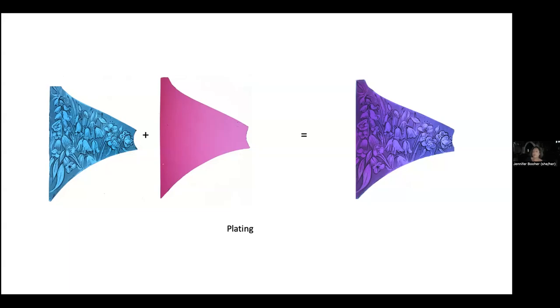The really interesting thing that Tiffany and LaFarge popularized is called plating. Neither was the first to do this, but they took it to a new level and it became a hallmark of the opalescent style. Overly simplified, it refers to layering pieces of glass to create new colors or atmospheric effects. For example, painting done on a piece of blue glass, when layered over pink, looks purple — and in real life there would be a depth to that color you wouldn't get from a single piece of glass. These pieces would be set in lead came as a kind of sandwich. The technique is also sometimes used in conservation to match historic glass colors that aren't made anymore.